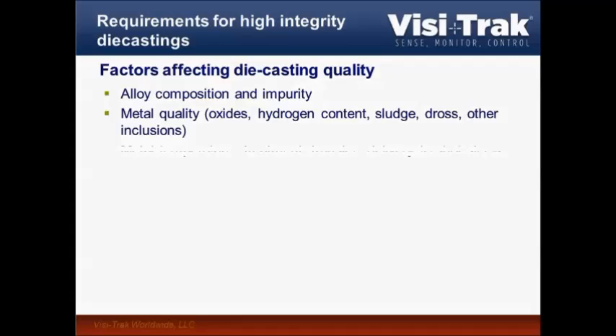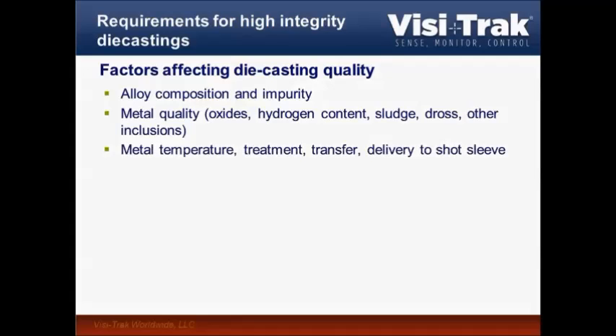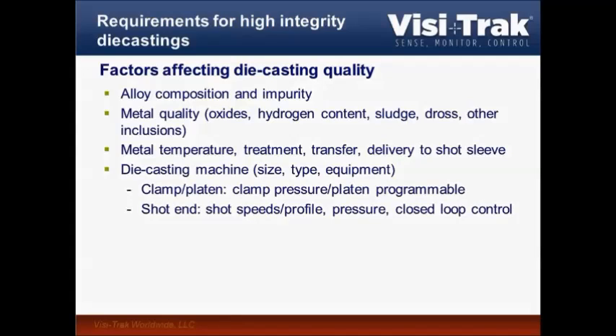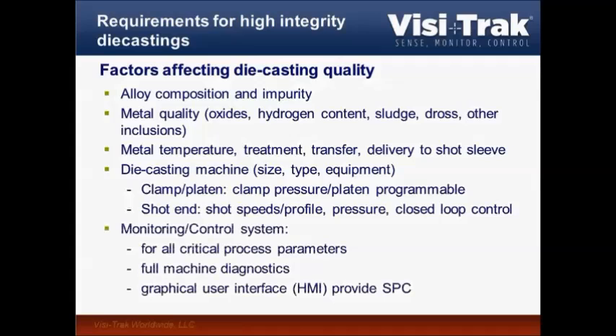Then the already mentioned sludge, dross, and all sorts of other inclusions. The metal temperature shouldn't be too high and certainly not too low. The metal treatment, the transfer, and ultimately the delivery to the shot sleeve. Then the die casting machine, which size, type, equipment, clamp platen, the shot end, pressure, closed loop control, and so on. The monitoring and control system of the die casting machine for all critical process parameters, full machine diagnostic, and of course, ideally, we want to have a graphical user interface and provide SPC data.